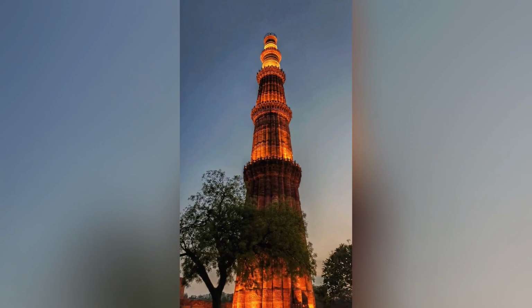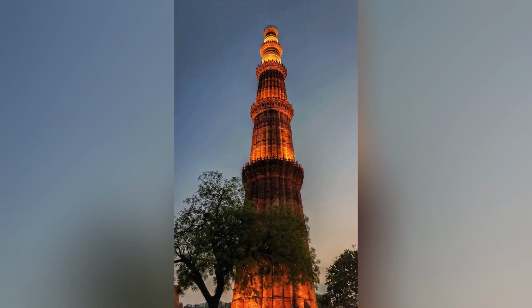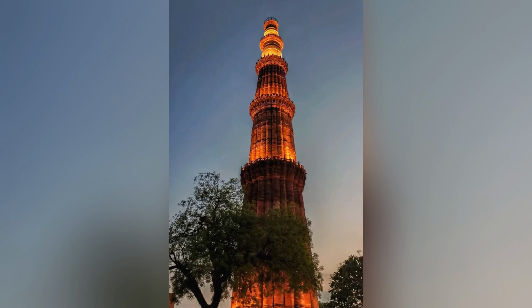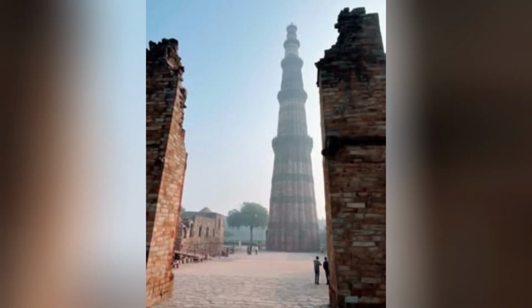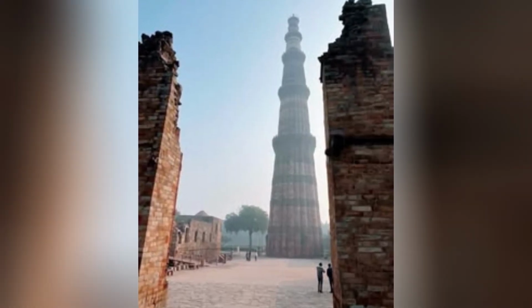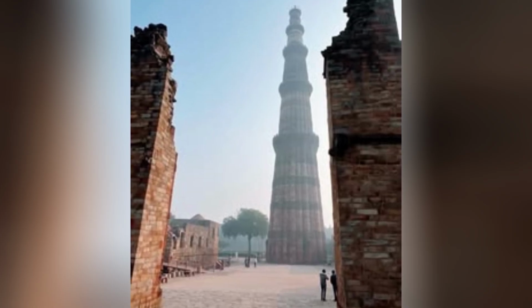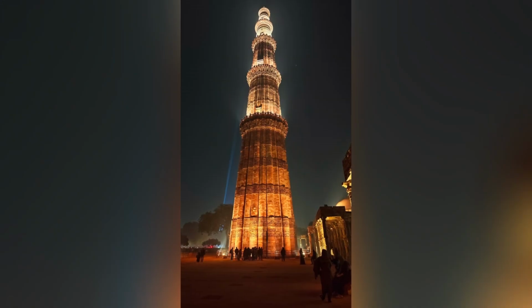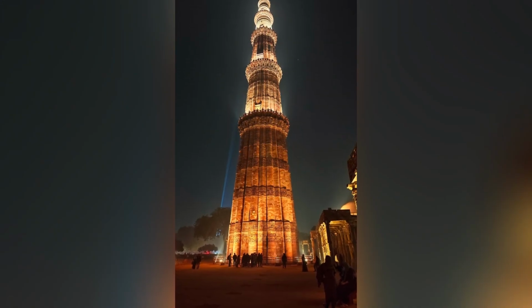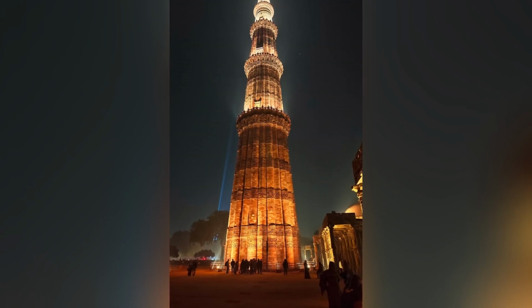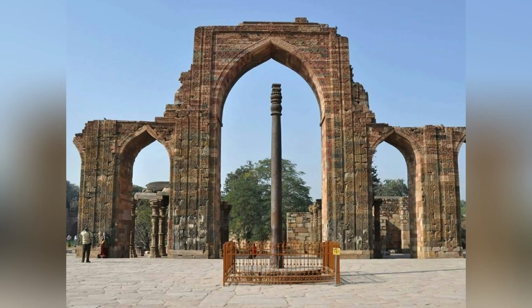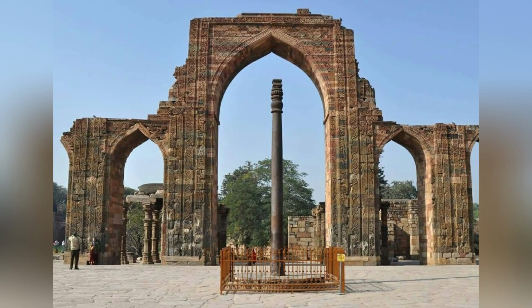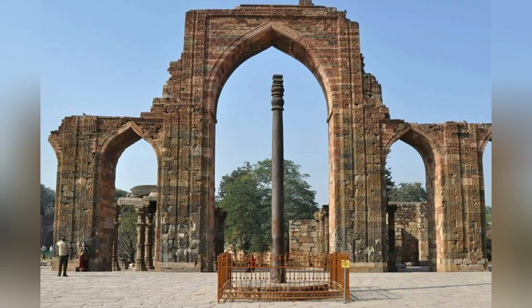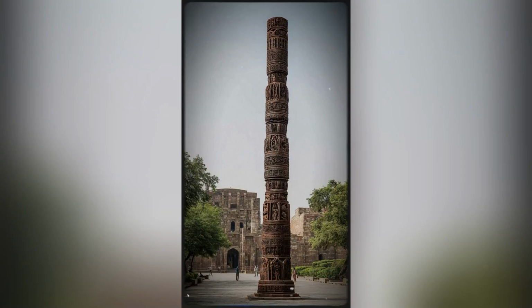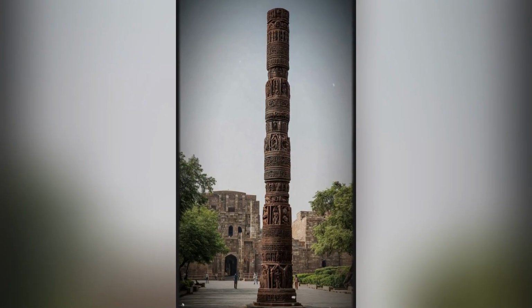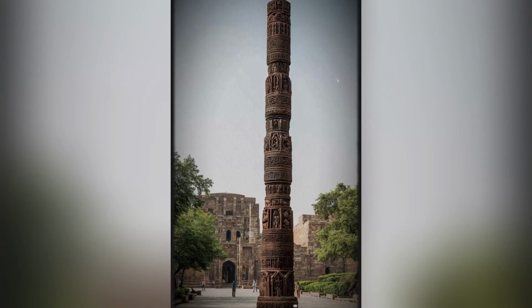The production of a 6.5-ton iron pillar using the bloomery process would have been a monumental undertaking. The bloomery process produces iron in small quantities, typically a few kilograms per smelt, and the production of a pillar weighing several tons would have required dozens or hundreds of individual smelts, each producing a bloom of iron that would then need to be forged, consolidated, and welded together with the other blooms to build up the mass of the pillar. The forge welding of multiple blooms into a single coherent mass is a demanding operation that requires precise control of the temperature and the timing of the welding, and the achievement of a pillar-sized weldment with a structural integrity to stand for 16 centuries is evidence of a level of ironworking skill that is extraordinary by any standard.